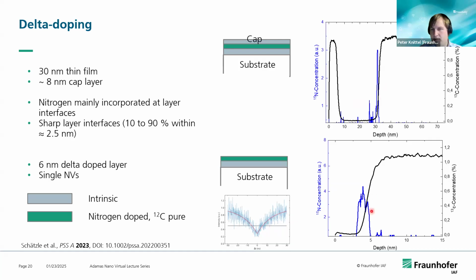So what you actually see here in blue is again the nitrogen concentration. We can even tailor our process in a way that only very close to the interface of this layer, we include the biggest amount of nitrogen, but we can also control it in a way that it's homogeneously distributed in this thin layer, as good as you can probably measure it using SIMS measurements. But what you see here is actually just a 5 nanometer layer on the very top of the diamond substrate.